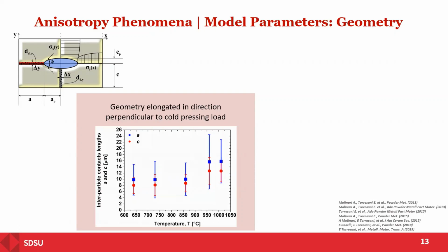So you said that one way to find out the geometrical changes is through simulation. But what can you actually do with finite element? Because you talked about deformation, you're not talking about anything else. So what one can maybe do is assume different geometries of your particles, then assemble three or four of them, apply a stress and keep track of the deformation. Then you will get a very nice idea of the change in the geometry as a function of applied force.